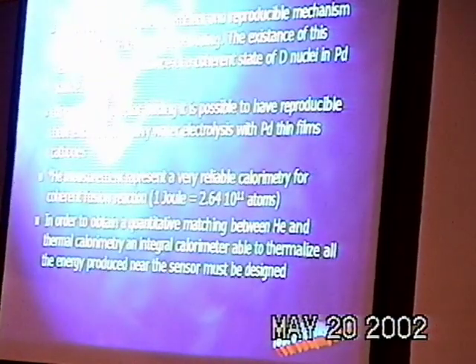But what we measured: the fusion temperature of palladium is 1800 K, and we expected from the Stefan-Boltzmann law, assuming that only 5% of the cathode had suffered this effect, 1.2 watt. But our Peltier element measured just 20 milliwatts. This is the proof that this is not right calorimetry. We had to add more. It's not enough. So, conclusion.